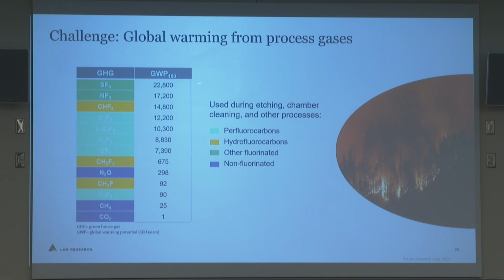So you saw my example of wanting to etch silicon dioxide using CF4. There are a lot of other carbon fluorides or carbon chlorides that are used for etching. NF3, nitrogen trifluoride, is commonly used to clean the deposition chambers, because anytime you deposit on a wafer, you're depositing on the entire inside of that reactor as well, and that material eventually needs to be cleaned off to be able to continue.